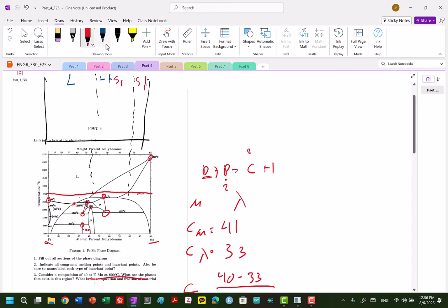So we know when we're in a two-phase region, we need to have, let's just do this here. We need a common tangent. And that common tangent means that the chemical potentials are equal and also that the slopes are equal. So we're lowest phase here. We're going to touch and then disappear. Here we have to be higher because lowest free energy wins.